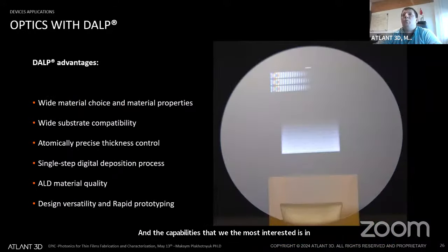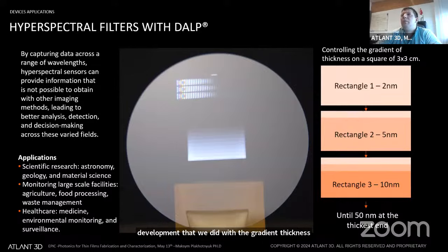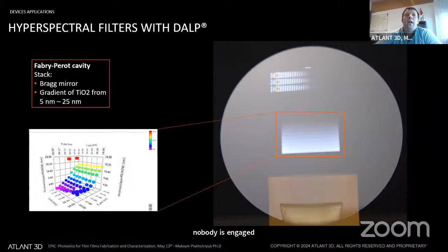So just to highlight the development that we did with the gradient thickness filter, this is how we did. We made bigger squares with one thickness, then we reduced the area for rastering to 5 nanometer thickness, 10 nanometers. We can really control it. It's like an overnight process where nobody is engaged. We just leave it and the machine does the work. And in the end, you could see here the control over the thickness. We did the test measurements confirming what we wanted to achieve.